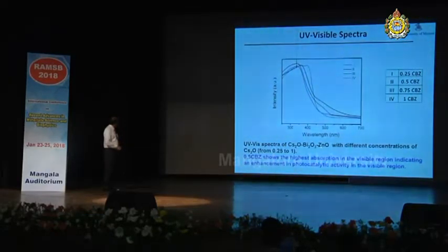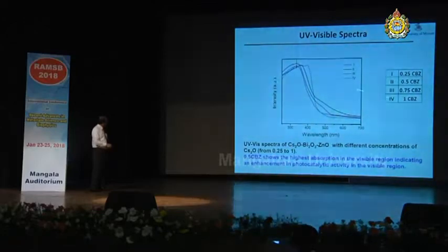And UV spectra of this composite with different concentrations of cesium. We have varied the concentration of cesium from 0.25 to 1 molar. Sorry, the standard solution is about a 1 molar solution we prepared for this, and we changed the concentration from 0.25 to 1 molar in the synthesis of this composite. And when you have about 5 milliliters of this 1 molar cesium oxide solution with 1 millimolar of the bismuth and zinc nitrates, the raw materials,